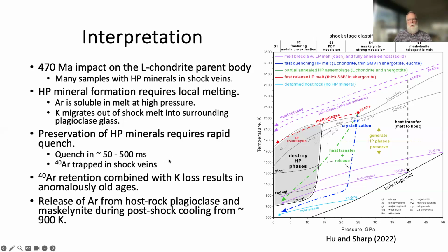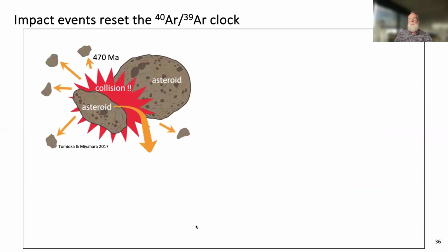Preservation of high pressure minerals requires rapid quench. That rapid quench traps the Argon-40 in the melt vein, but apparently not the potassium. Okay, so you've seen all that before. So here's what's going on.